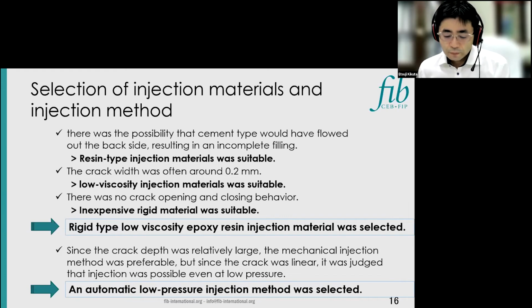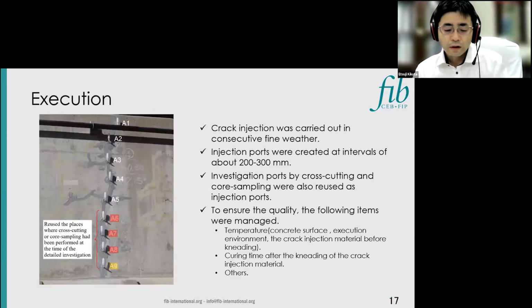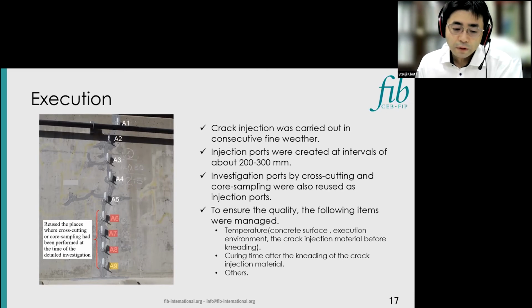As for the injection method, since the cracks were linear, it was judged that injection was possible even at low pressure. So, the automatic low pressure injection method was selected. The photo shows the actual injection situation. Here, air pressure injection type devices were used. Since water leakage occurred from cracks during rainfall, it was carried out in fine weather. Injection ports were created at intervals of about 200 to 300 millimeters, and investigation ports by cross-cutting and core sampling were also reused as injection ports.